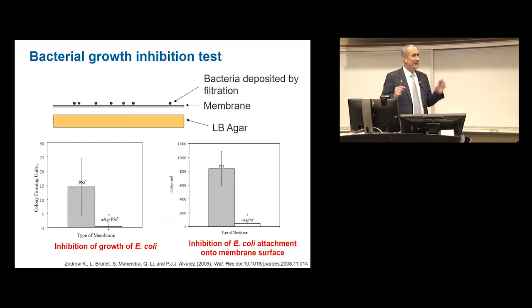These were microfiltration membranes with relatively large pores. So we set the membrane on top of a nutrient agar, and this allows food to get through the membrane, and if the bacteria are alive, they begin to grow, and they form colonies that you can see with your naked eye, and you can count them. And the point is that the silver impregnated membrane was very successful at preventing bacterial growth.